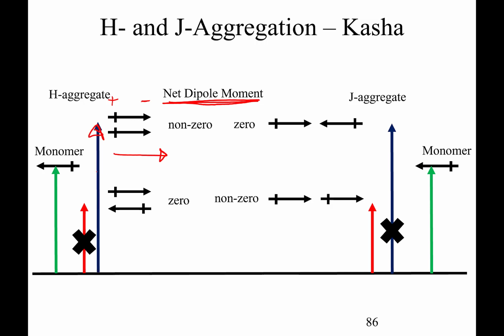The lower energy state, when we have opposing transition dipole moments, well, the net transition dipole moment, because they're opposing, is 0, but it's a lower energy state because we've got the plus charge here and the negative charge here, and they actually attract each other. So it's a lower energy state, but there's no absorbance allowed because there's no transition dipole moment. So that's an H aggregate for you. And if we have a J